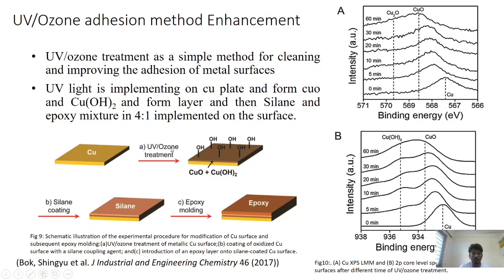Now this is the procedure of the ultraviolet or ozone treatment with the copper substrate. In this method, copper metal was exposed to UV light with wavelengths of 185 nanometer and 254 nanometer, in which when the UV light is exposed at the surface of the copper substrate, copper is oxidized to copper oxide and copper hydroxide, which can be seen from these two graphs. This is showing the intensity and the binding energy of the copper oxide and the copper hydroxide.